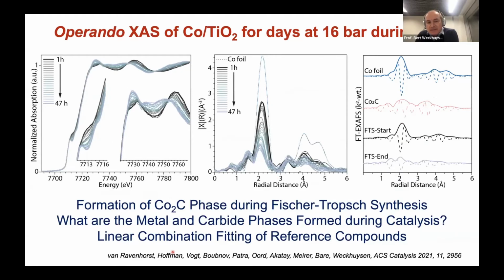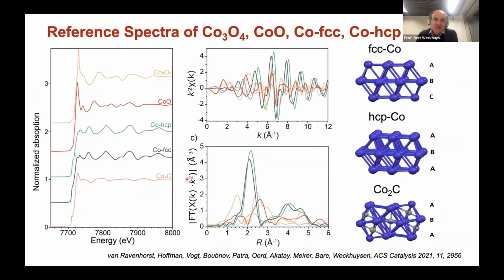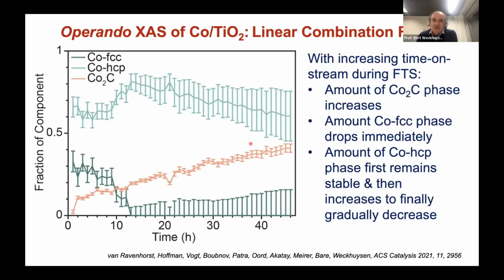What about another way? If we do a linear combination of reference compounds, what are the reference compounds? Cobalt oxide, two forms, the HCP, FCC of cobalt, and the cobalt carbide. And here I show you the structures. If you take this, you can do a fitting. And now we did a lot of fittings.